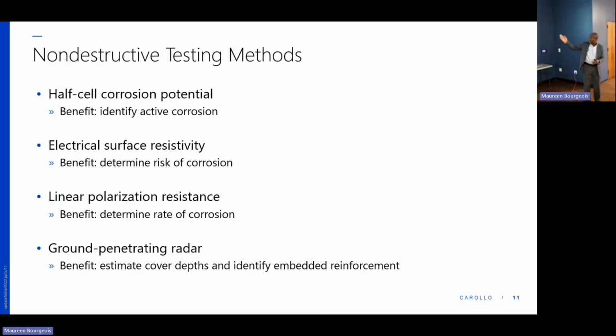The various test methods that you see there, the half-cell corrosion, electrical surface resistivity, linear polarization, and ground penetrating radar, these are what I'll call equipment-based readings. So pretty much it's equipment that you either put to the face of the concrete or you connect to the reinforcing by drilling a small hole and attaching a cable to get to the reinforcing, or it's equipment, depending on it, you connect to both the concrete and the steel to get a reading. And so that is what all these four tests give us. So it's a handheld device and equipment connected to these things to be able to get the reading.